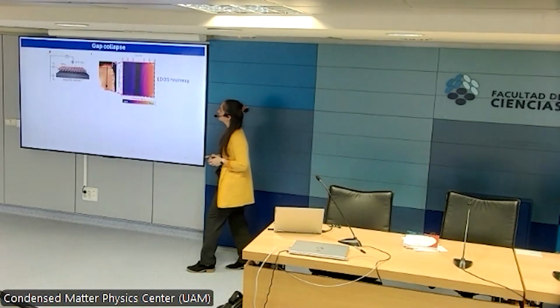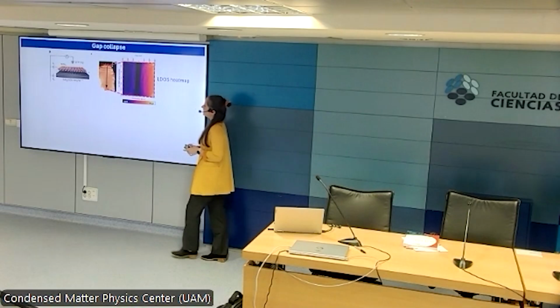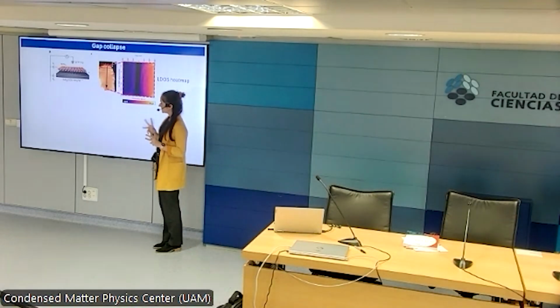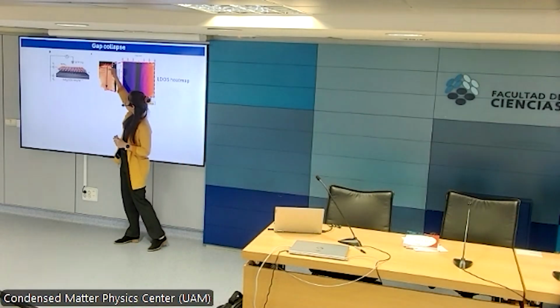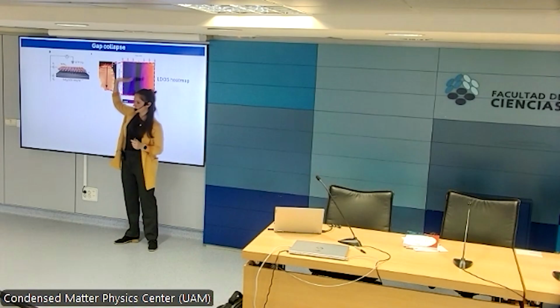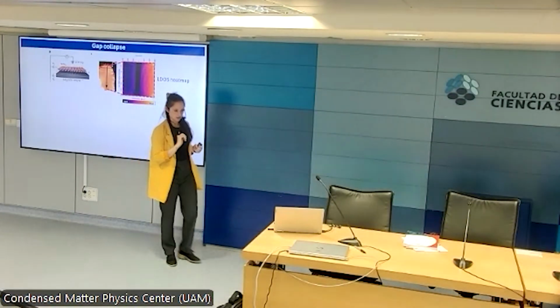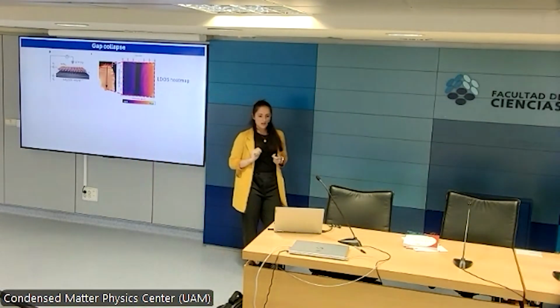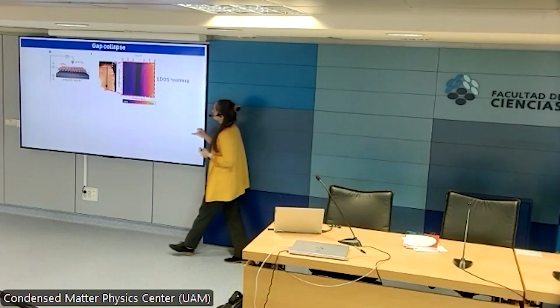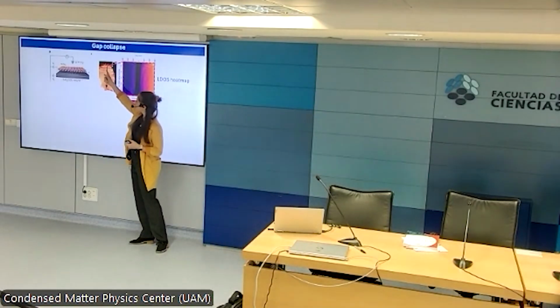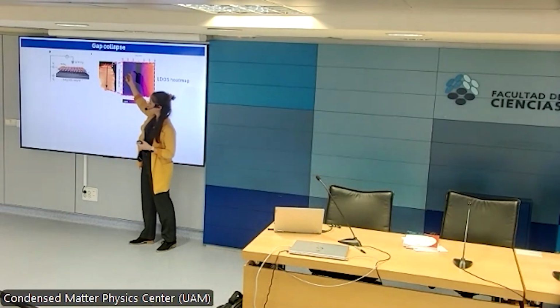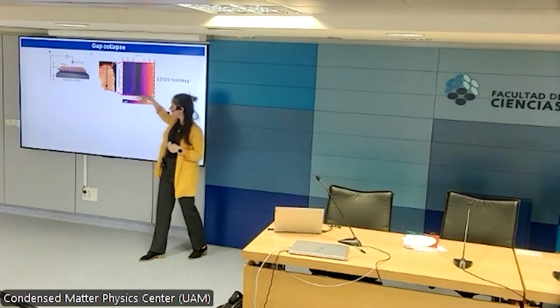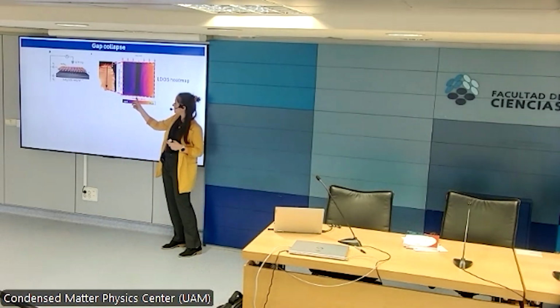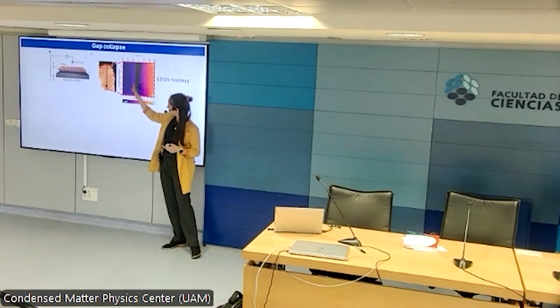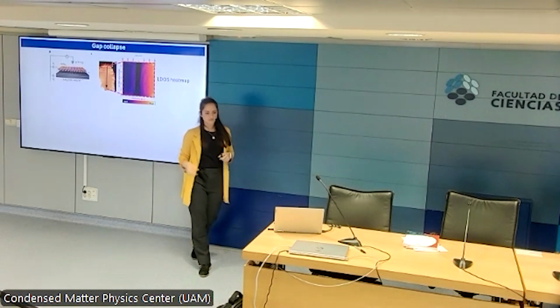We want to check now if we can demonstrate that this is an excitonic insulator. To do that, we look at the density of states in the 2D bulk. So this measurement here is done by excluding the 2 nanometers that are at the edge. We are not looking at the topological insulator state now. And what we do is acquire a series of dI/dV, so local density of states maps at every point here, and plot them, which are plotted here as a heat map. Black is where the band gap is, and then purple, orangish is where states are.